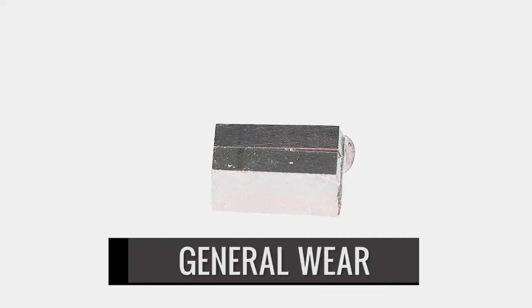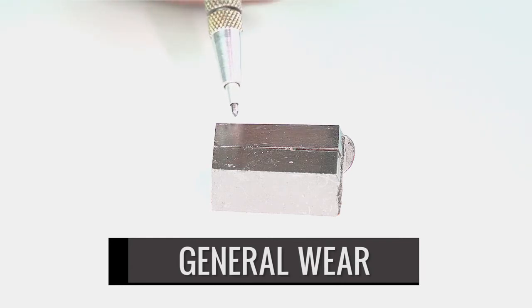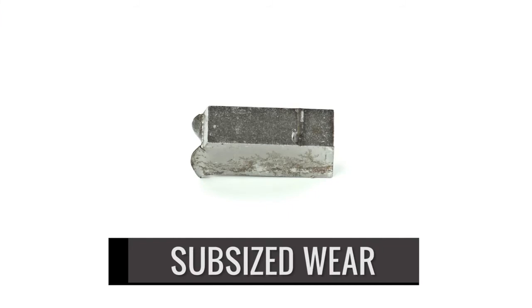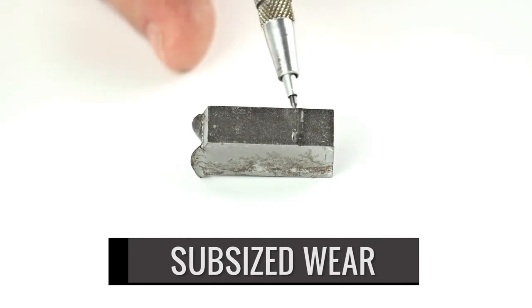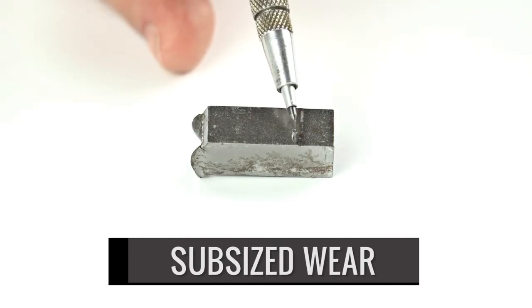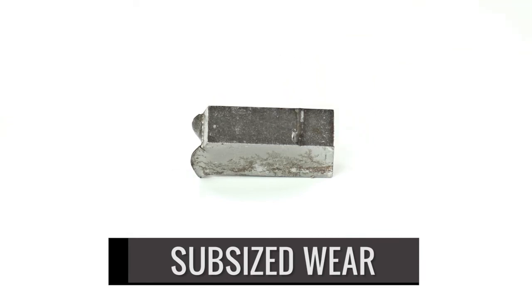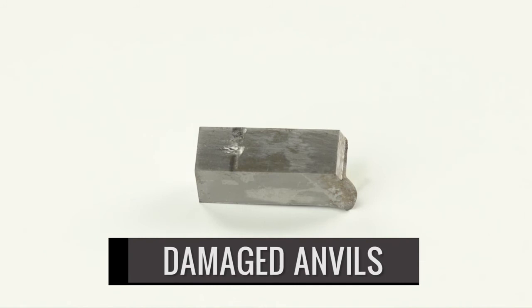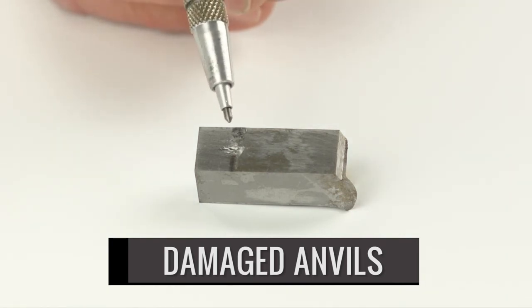General wear changes the normal anvil markings from clearly delineated markings to a more smeared mark that progressively smears as the wear increases. Wear from subsized specimens is distinctive because the anvil mark changes abruptly at a position relative to the thickness of the subsized specimen that resulted in the wear. Sometimes anvil marks on specimens are difficult to characterize without inspecting the anvils directly. However, non-uniform markings like these are not acceptable.